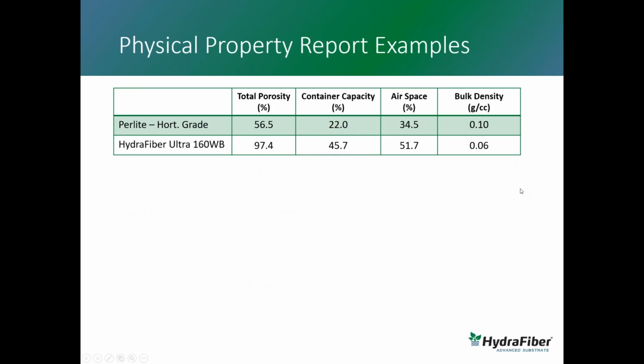So now let's look at how Hydra Fiber compares to Perlite. I mentioned a few moments ago that most of our customers are looking to remove Perlite completely. It makes a pretty good substitution in the substrate. Let's look at how the physical properties of a typical horticultural grade Perlite compare to Hydra Fiber 160. I'm using 160 here as an example because 160 is the grade of Hydra Fiber that most of our customers use starting out. If we look at the total porosity, we can see a huge difference between the Perlite and the Hydra Fiber. The total porosity of Perlite is under 60%, whereas Hydra Fiber is almost 100%. We're at 97.4% in this particular sample.